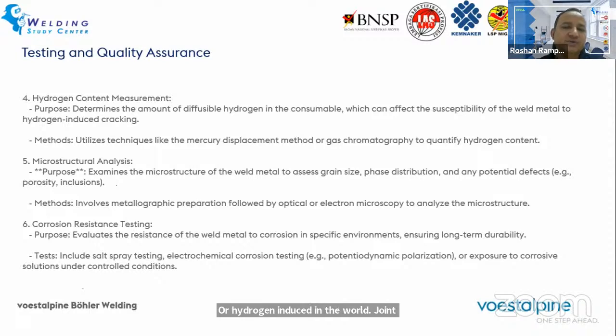So the diffusible hydrogen content is determined, and based on that, different classifications like H4, H8 are also given to the welding consumables. There are different lab methods to determine the hydrogen content. Then microstructural analysis of the weld deposit is also done to check the phases which are present, like ferritic phase, then bainite, then martensite, or whatever the secondary phases are present in the weld deposit,